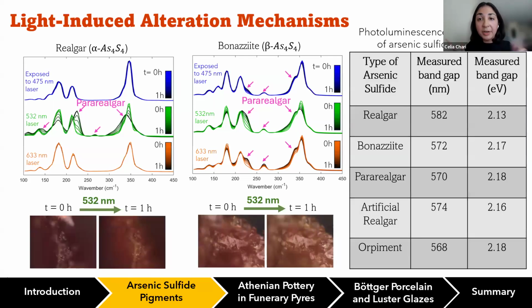I should say this relationship with green light exposure was found to be directly related to the band gap of these materials. Both realgar and bonazziite are semiconductors, and using photoluminescence, I measured the band gap and found that it was really close to that of the green light laser that we used. So this explains why we're seeing that is affecting it so much.